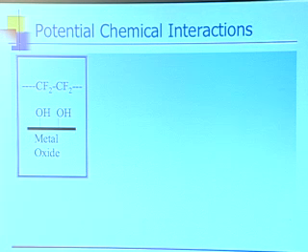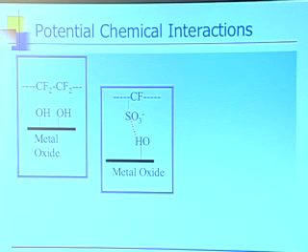So what could be happening there? Well, there's got to be a specific interaction of some sort between the metal oxide and the polymer based on the data we have. So one guess might be that the polymer backbone somehow physisorbs onto that metal oxide surface, which I'm showing as a hydroxylated surface, because certainly under the conditions of humidity and temperature that we're working at, there are hydroxyl groups there. That's one possibility. Second possibility is that there's a hydrogen bonding interaction between the sulfonic acid group on the polymer and those hydroxyl groups on the surface.